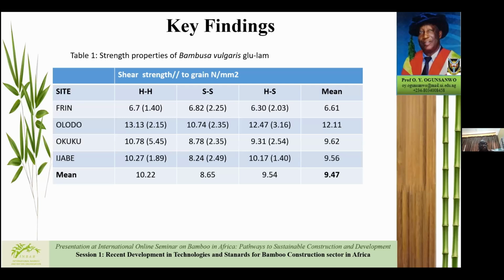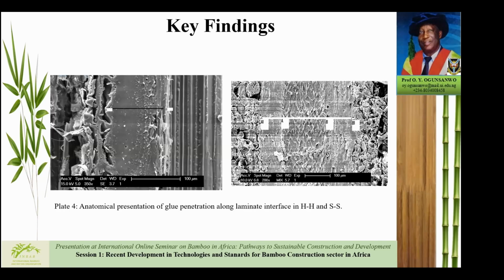our anatomical studies, when we try to cut the bamboo along the glue line, the test specimen along the glue line, we found that in plate 4, look at the distance from A to B. Distance from A to B is giving an indication that we have A to B as the 2 surfaces of the H and H specimen. And then between A and B, we have the glue that is loaded within the surface, within the interface.